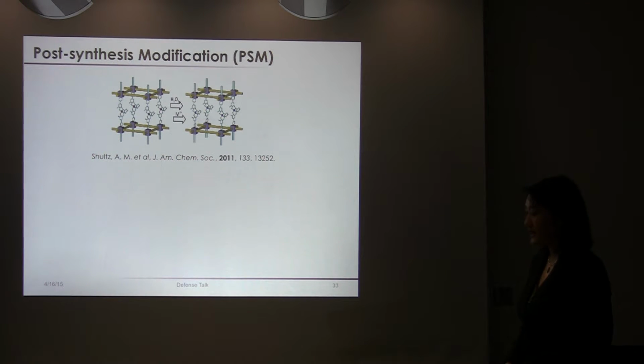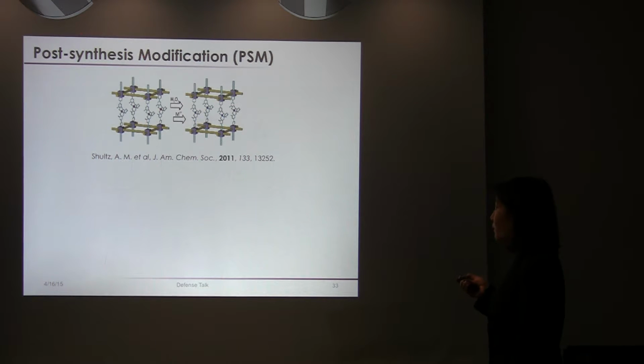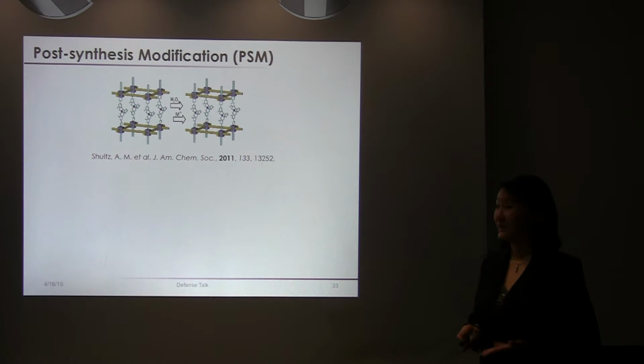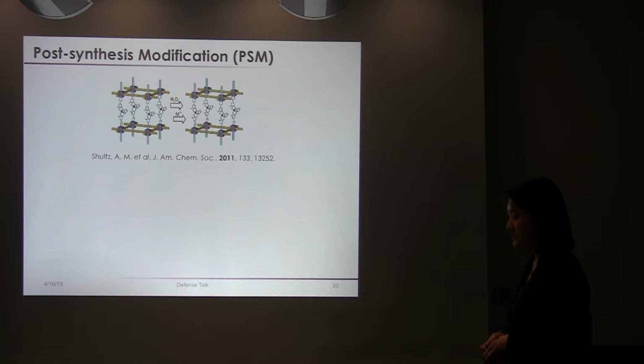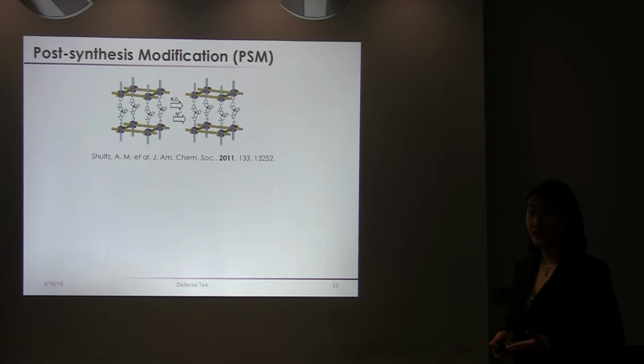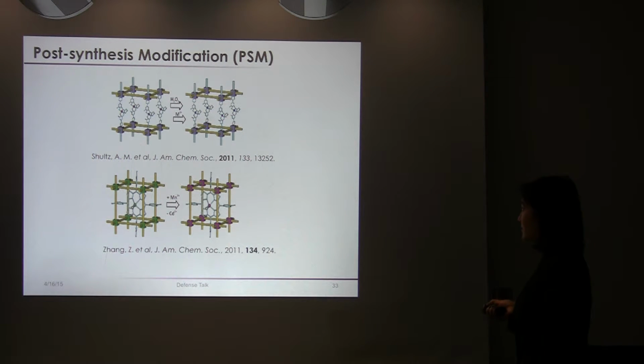Okay, so a promising partial solution to the aforementioned problems is what's called post-synthesis modification, or PSM. And this is essentially a chemical alteration of the framework without changing the parent topology. And typically, in both of these examples, a second PSM step is necessary to introduce catalytic metal sites into the MOF that are typically incompatible with de novo MOF synthesis.